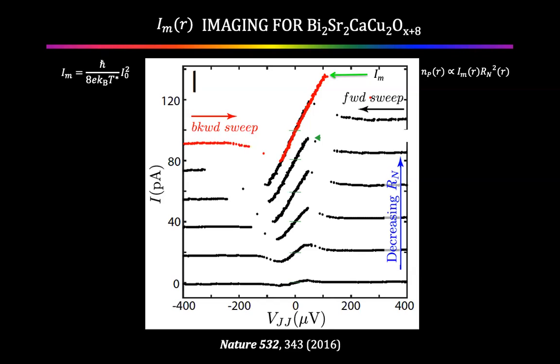And we have done a whole round of experiments of niobium on niobium diselenide to test our understanding of this problem. And we run into the same situation. In niobium on niobium diselenide, if the junction resistance is, say, 5 megohms, everything works fine. If you go down below 1 megohm, you start to see both Josephson and Andreev. And if you go down even lower, you get a very complicated combination of pair tunneling, Andreev bound states, and quasi-particle tunneling. So you have to go into the correct parameter range for this to work.